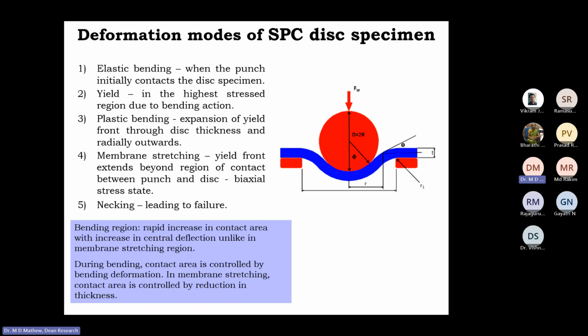The second point I wanted to mention is, among these three equipments, ball indentation, small punch creep, and impression creep, the cost of impression creep equipment is much less than small punch creep equipment, and it is less complicated. Only thing, you cannot get rupture data, but if you believe in the Monkman-Grant relationship, then as long as you have the steady state creep rate, you can derive the rupture life.